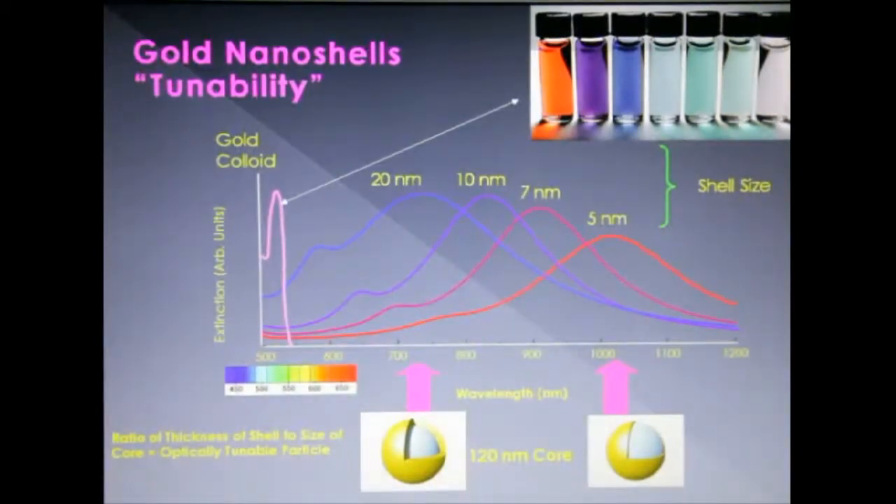In this region, the transmission through tissue is optimal. The gold nanoshells we synthesized have a 120 nanometer diameter silica core and around 14 nanometer gold shell, with a maximum absorbance at close to 800 nanometers.